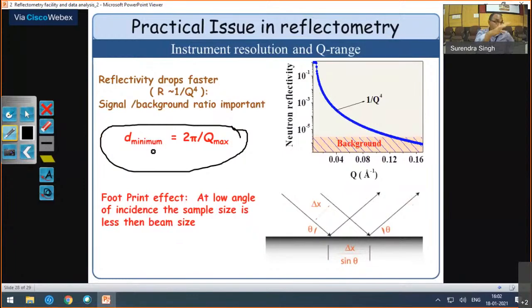You know, when we put a single layer on the substrate, then that reflected beam, the interference comes because of the path difference between the reflected neutrons from interface 1 and interface 2. And that phase difference gives you this relation, d minimum.